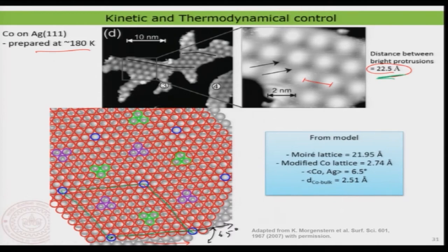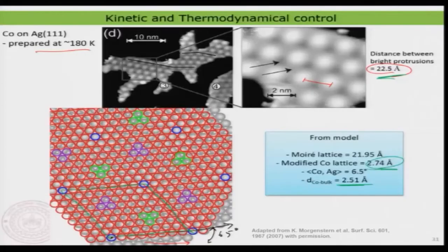So, to get this, I also have to do a small modification in the cobalt distance. That modification is about 2.74 angstrom. Compared to the bulk lattice, in this particular case, in order to get this microscopic model correct, I need to slightly adjust the cobalt distance. And if I do that, I can clearly reproduce the experimental parameters, which are the rotation, the angle between the adsorbed lattice and the silver lattice, and also the super periodicity of the Moiré lattice. If that comes out correct, the only adjustment I have to make is the change in the lattice parameters of the cobalt.